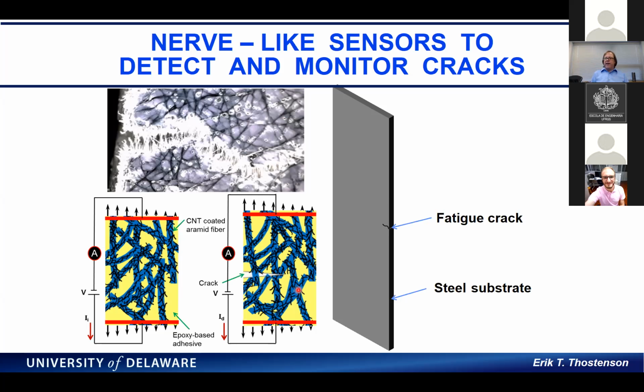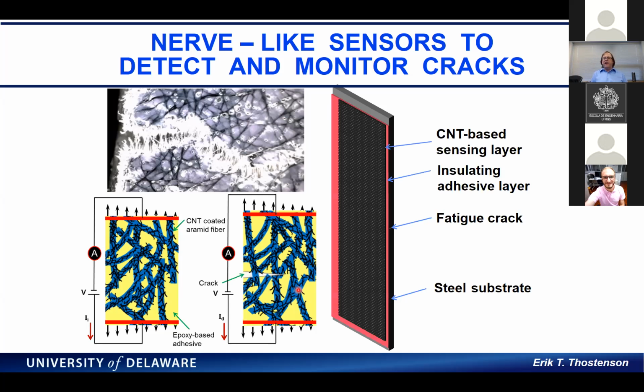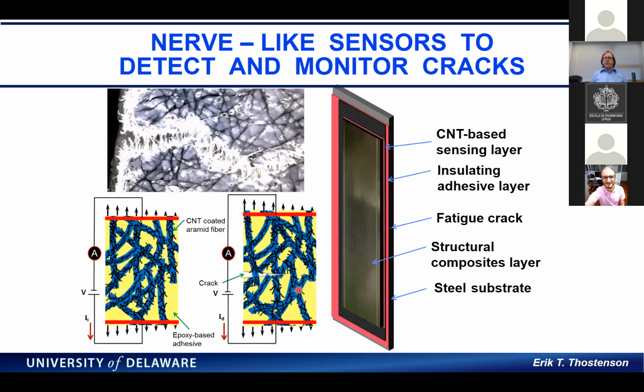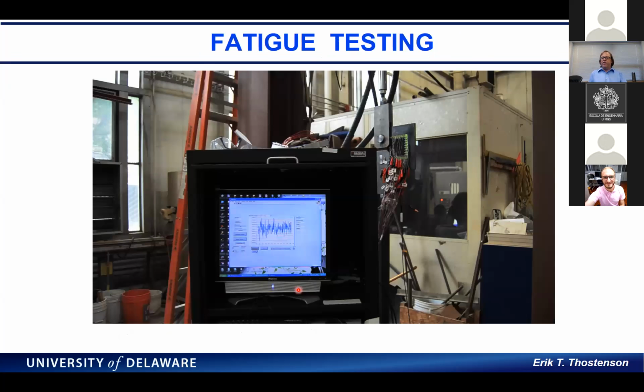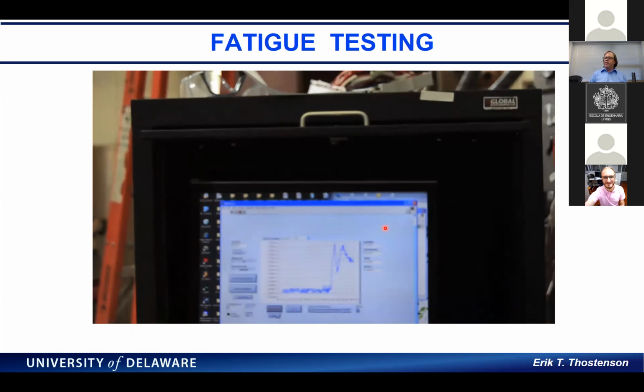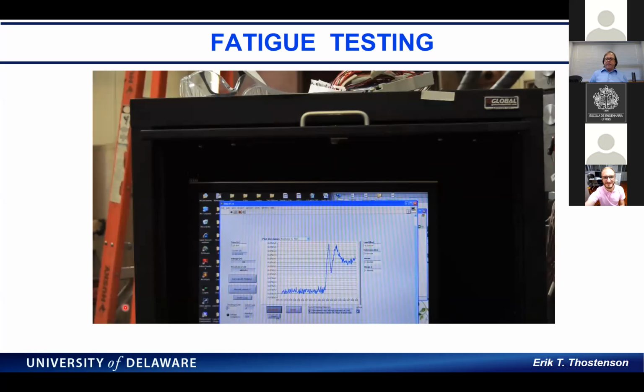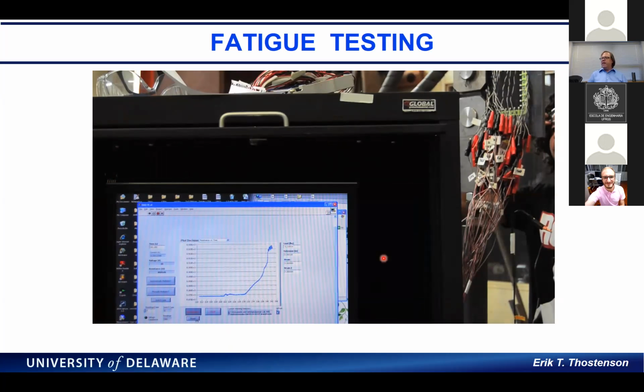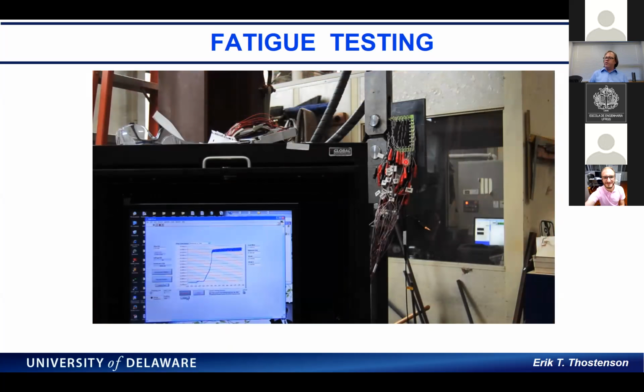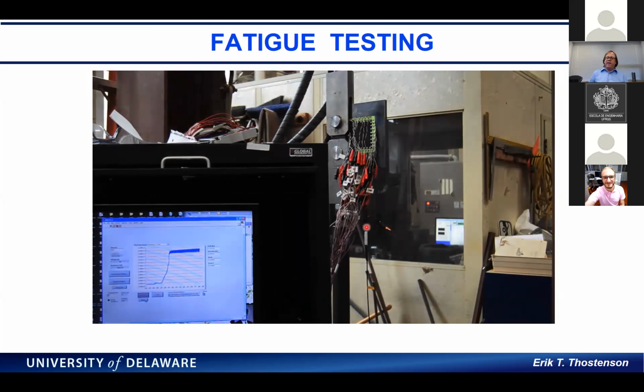And then I think there's an animation here. What we do is apply a very thin insulating layer, and then we apply our nanotube sensing layer, and then we apply a structural composite layer to also serve as a repair. We can use it with or without the structural composite. And then we apply our electrodes for sensing. This is actually a patch, and here we're doing impedance tomography. You can see on the right-hand side there are a lot of electrodes, but we're not using all of those electrodes in this measurement.